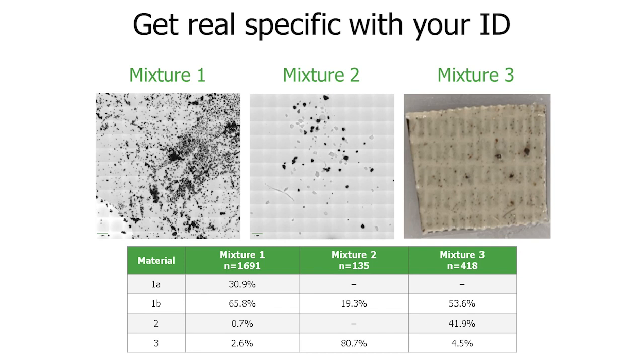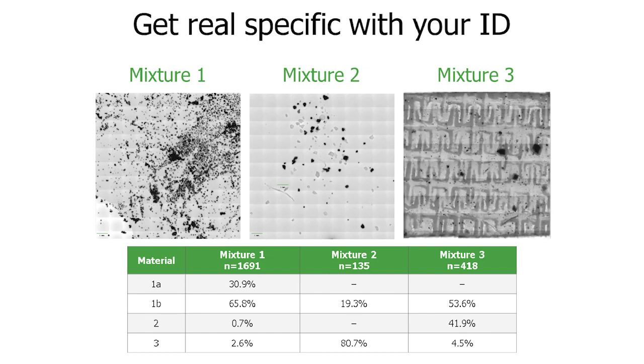Moving on to mixture 3, this had a few large particles and many small particles, so we're looking at a variety of particle sizes. One interesting thing about mixture 3 that you can see from this image is the particles are actually adhered to duct tape, because that's how the researchers collected the particles from the structure failure. The duct tape substrate presented no problems for Hound because LIBS was used, and duct tape is actually LIBS inactive.